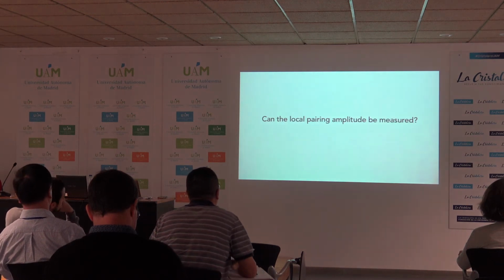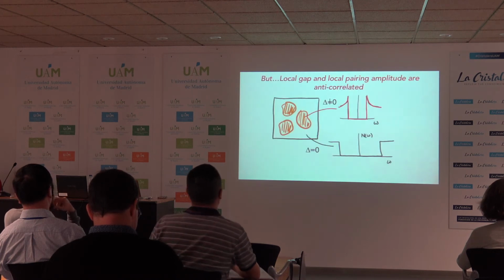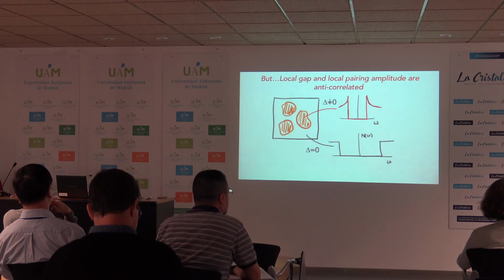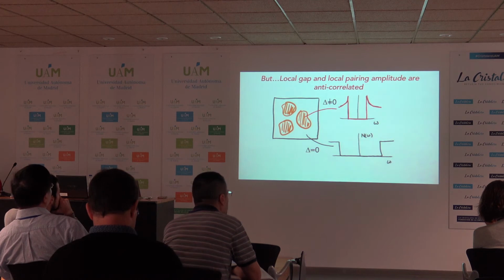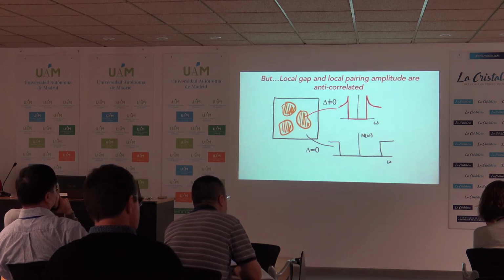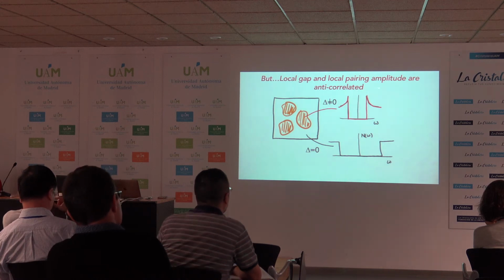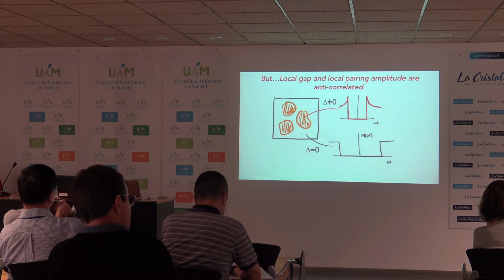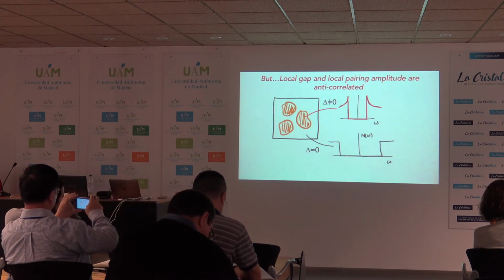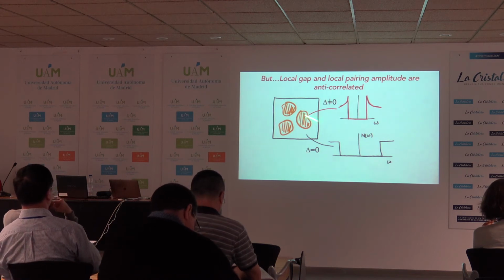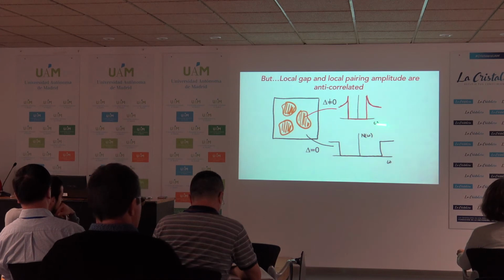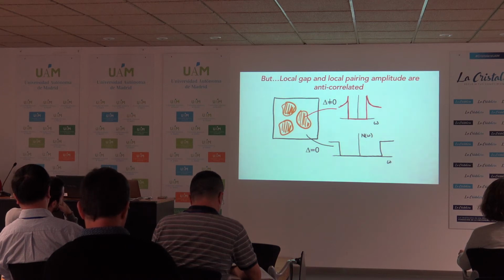Now, you might ask, can this local pairing amplitude be measured? You might think the gap is essentially revealing what my order parameter is in the clean system. So just do a tunneling experiment on the patch and in the region outside that. And you may have thought that if delta is zero, the gap should be zero. But what I'll show you is that the local pairing amplitude and the local gap in the spectrum are anti-correlated. So that's one very important result. The spectra on the patch will show this nice coherence peak and a gap scale, but when you go into these white regions, the gap scales are larger and there are no coherence peaks.